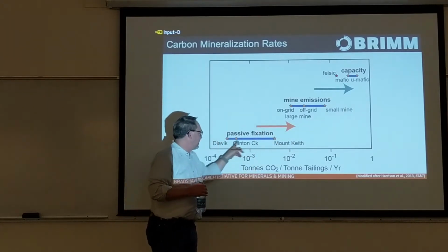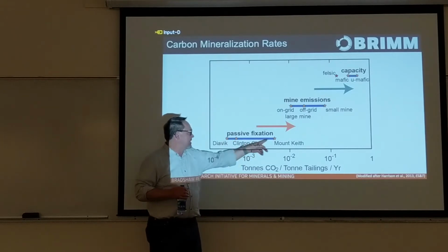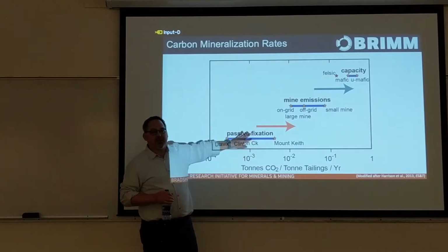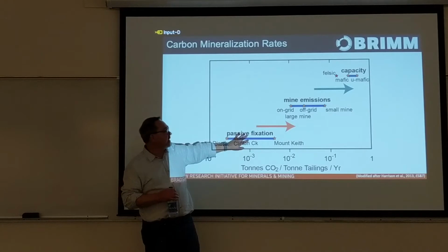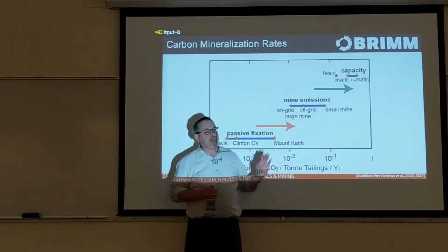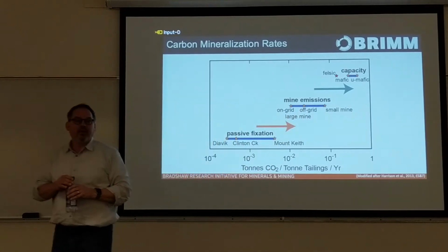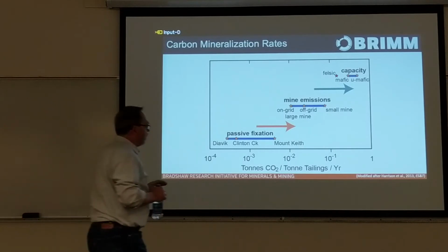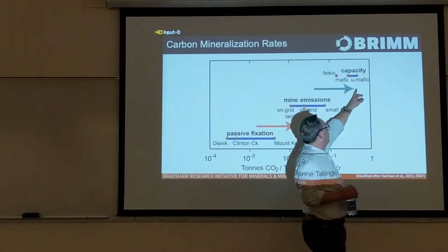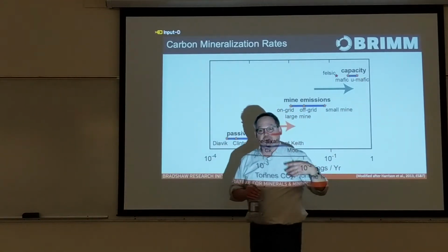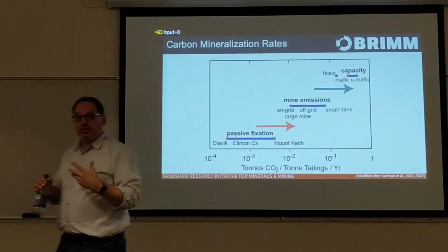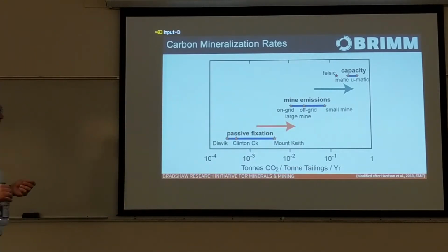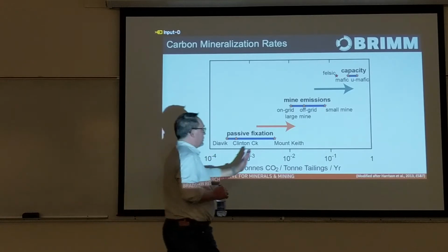And we can see that for different mine sites, these rates, this purely accidental carbonation that's happening in tailings, is typically at least a solid order of magnitude off of mine emissions. But importantly, the actual capacity of ultramafic host rocks to sequester CO2 is another order of magnitude higher. So if we can do roughly 10% reaction of our tailings, we have a greenhouse gas neutral mine.